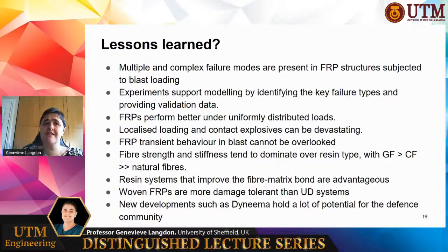And one of the particular areas that are difficult there is how you fix the conditions of the panel at the boundaries, which is quite difficult to replicate in an experiment. So what that means is that we need to model the actual boundary conditions used in our experiments so we can subtract that away from the material response and get to what's really important. Fiber-reinforced polymers are much better under uniformly distributed loads, as localized loads and particularly contact explosions, where the explosive is in contact with the material, are devastating in an FRP.